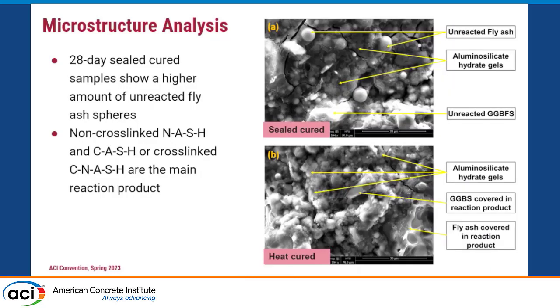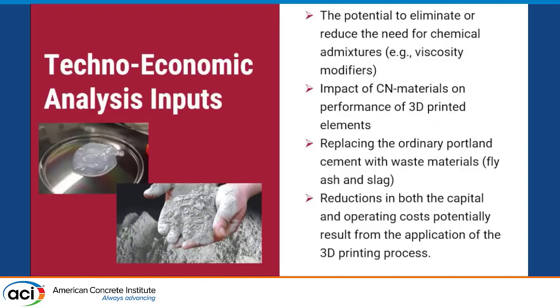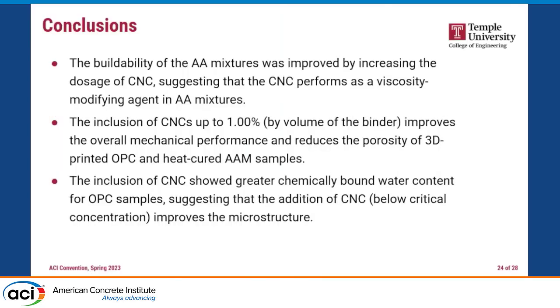This is an observation again from SEM, the main product. In the upper picture, you can see a lot of unreacted fly ash in the seal cure versus the heat cure, which is minimal. As I said, we introduced some of this as input for a techno-economic analysis. I'm going to skip this one due to the time limit.